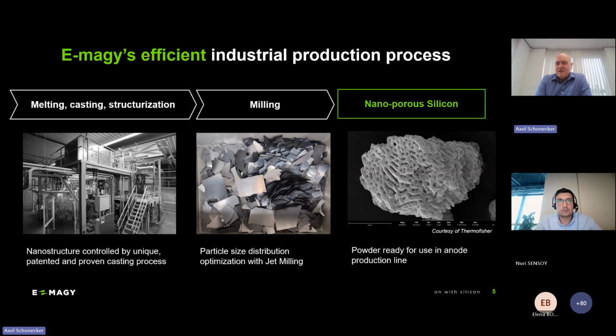The silicon, each particle has channels around 200 nanometer in diameter that go all the way through the particle. And this inner porosity can be used like a sponge to compensate for the expansion of the silicon. And that allows us to make stable particles that don't break and that cycle very well in lithium-ion batteries. So we have a couple of advantages here. We have a material that has demonstrated that it works. And we have a supply chain that is completely based on metallurgical processes. So we can actually scale with this sort of equipment in a very natural way.